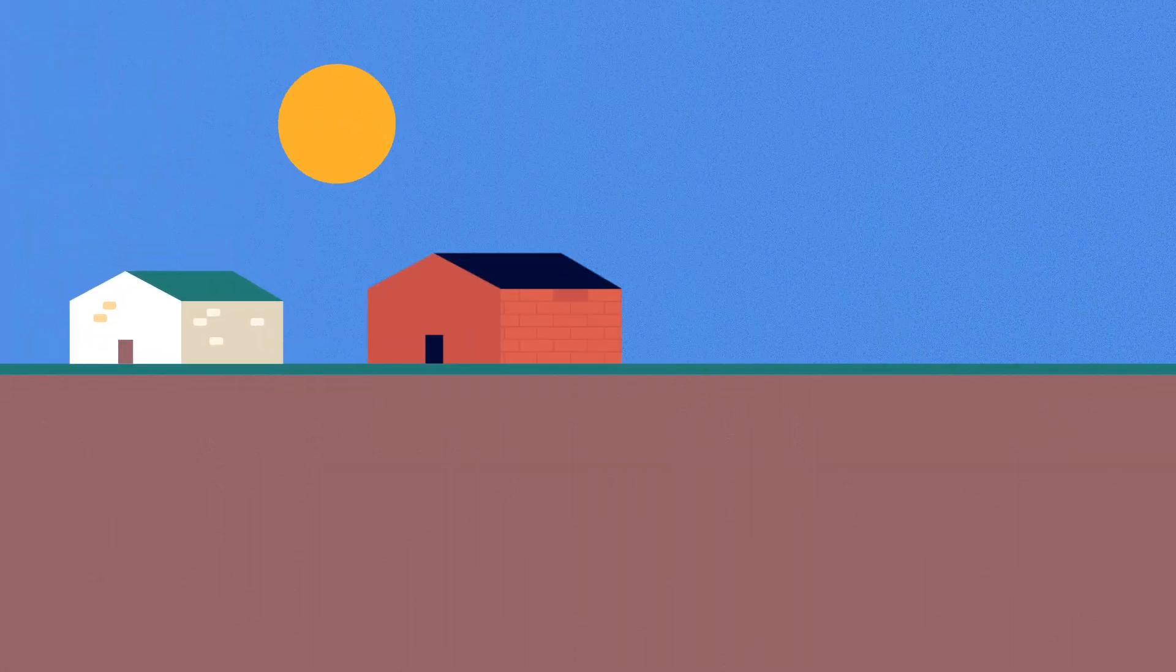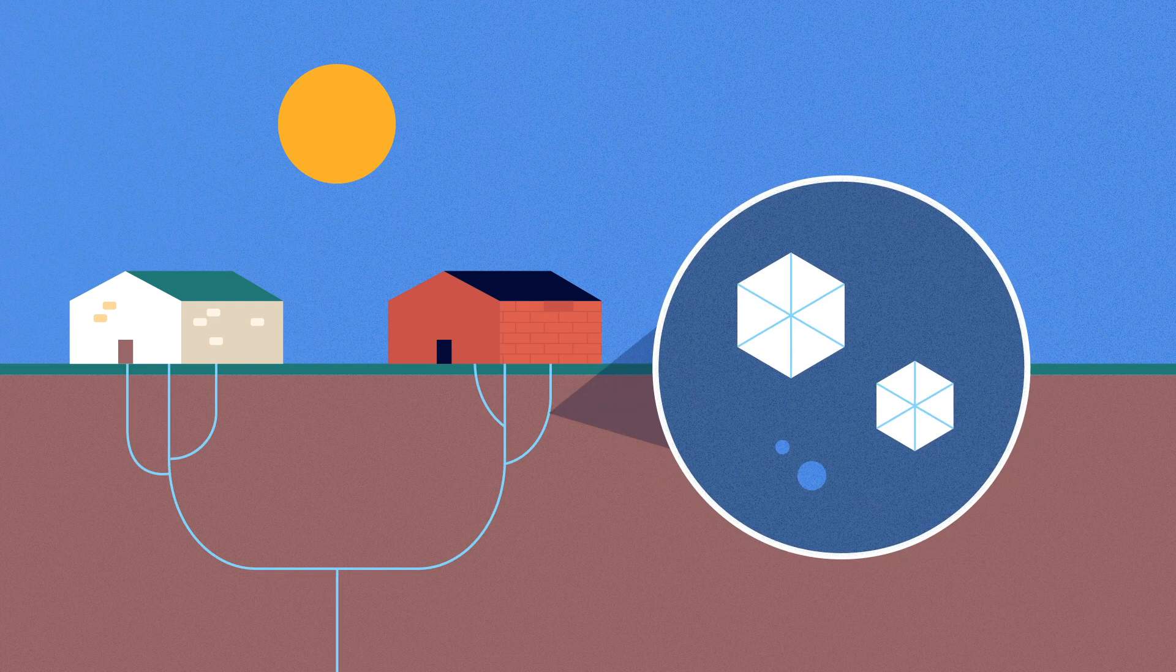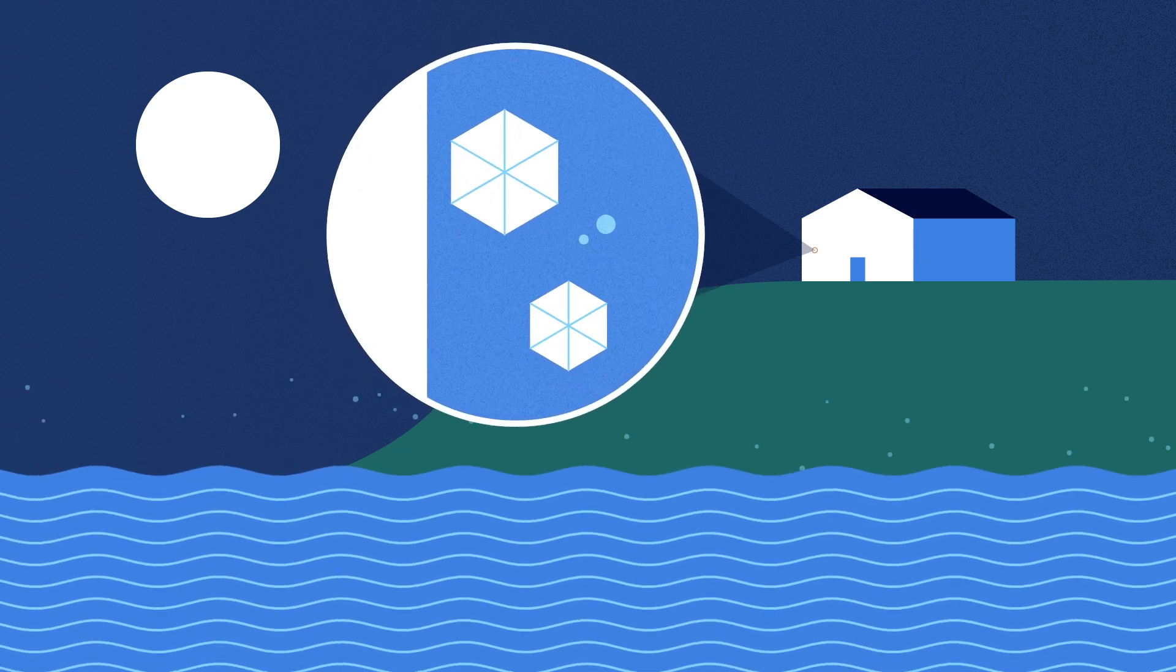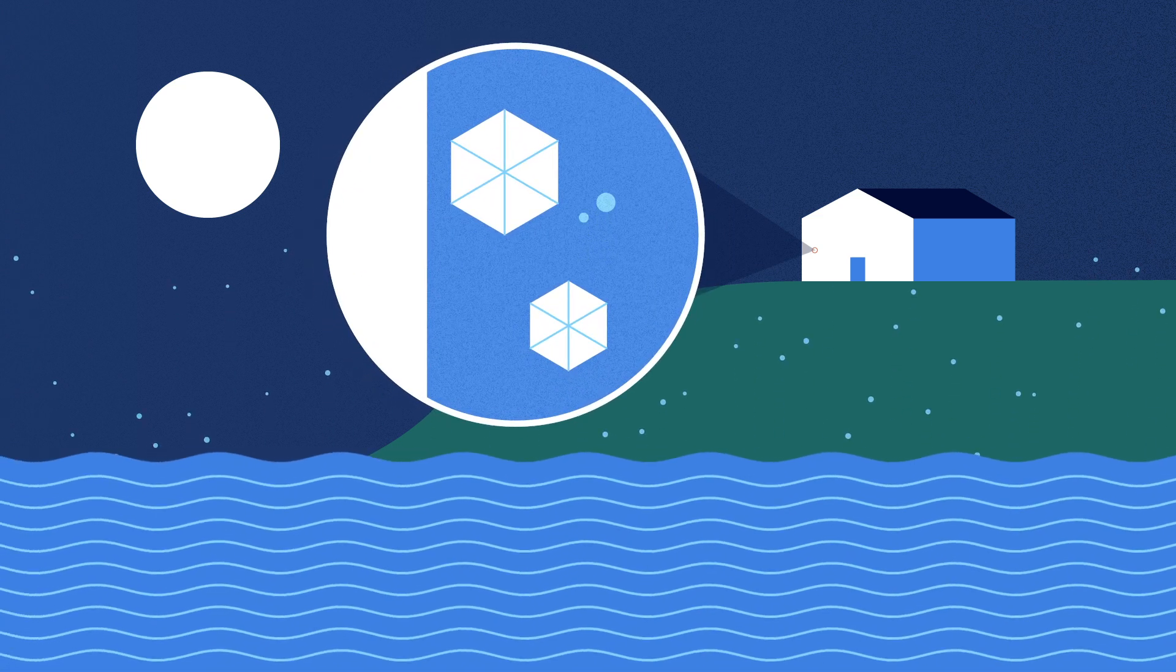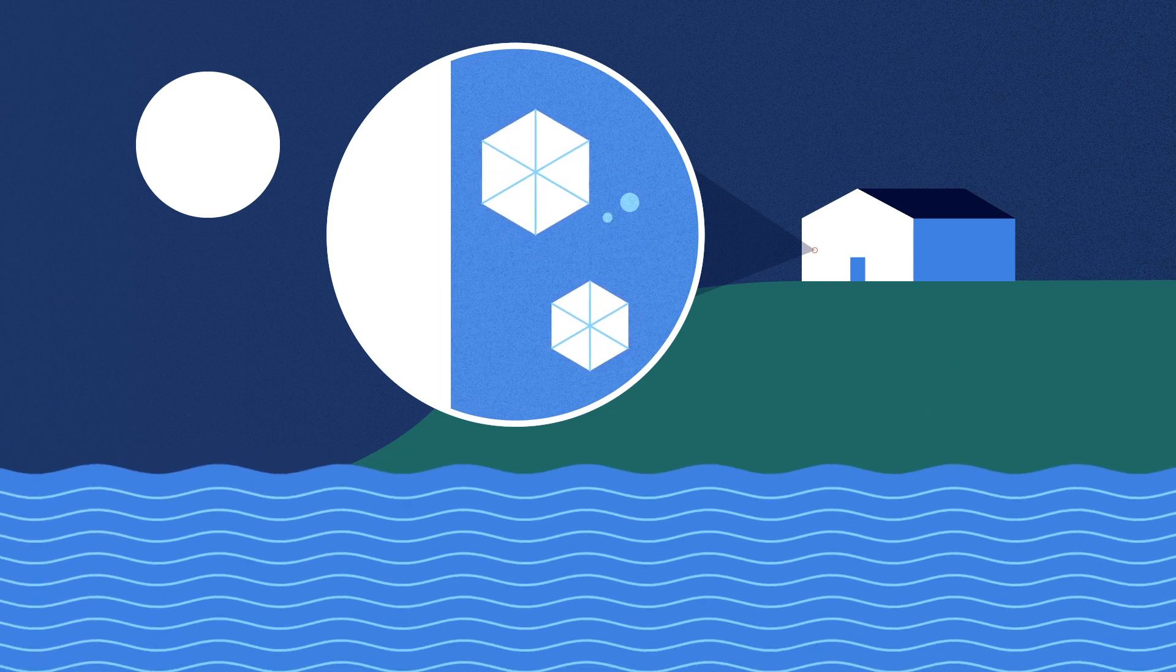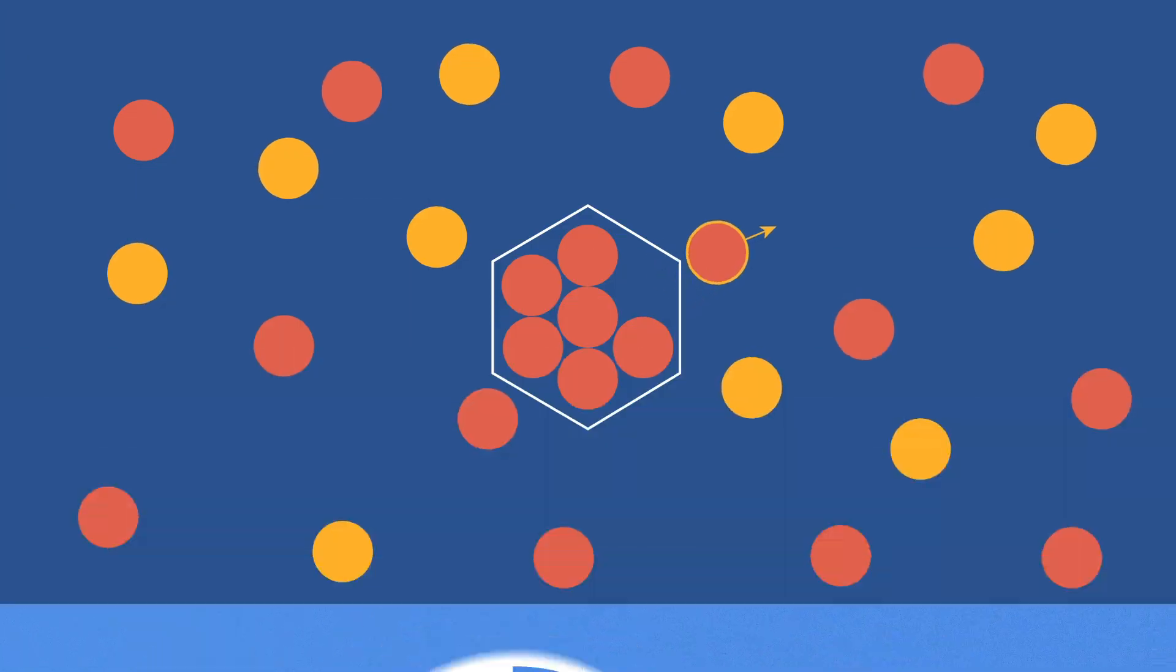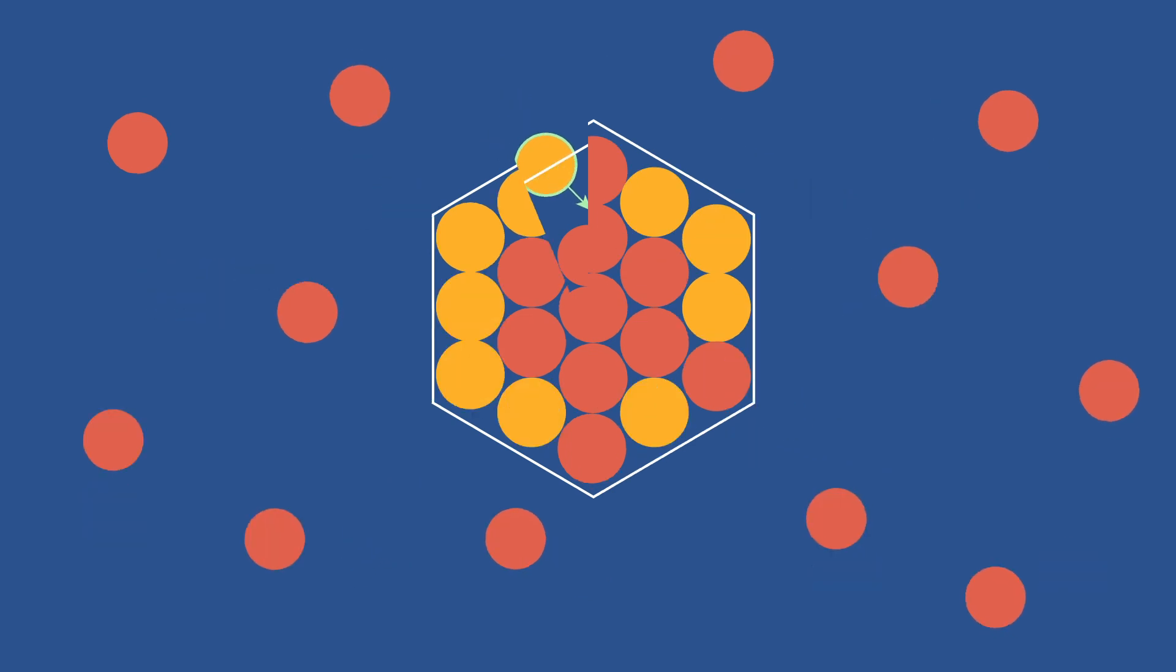In stone and brick, salts are most often supplied from an external source, such as capillary rise of groundwater, or, particularly in coastal regions, aerosols. In such cases, salts are supplied as a solution that gets concentrated by evaporation, either continuously or cyclically from changes in atmospheric conditions. If the solution becomes supersaturated, salts may grow within the pores.